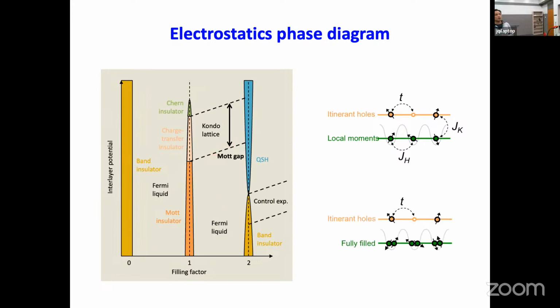And another control experiment that we can do nicely is by just looking at a doped band insulator. In this particular region here, the MoTe2 layer is kept at filling factor equal to 2. So we have 2 electrons, they form spin singlets at each site here. And then we dope additional free carriers into the tungsten layer. So that's corresponding to this region here, okay? And we would expect no Kondo physics in the system because we totally quench the local moments.